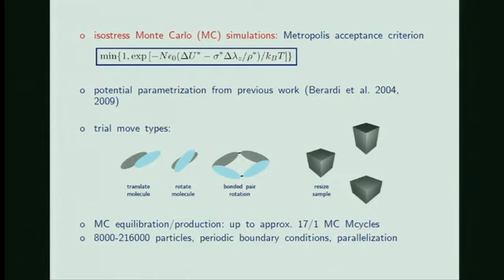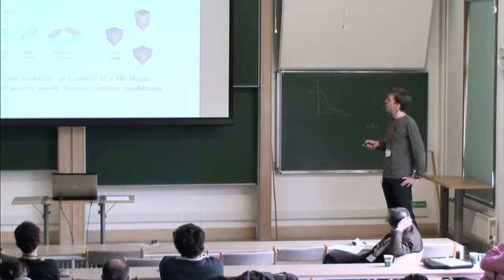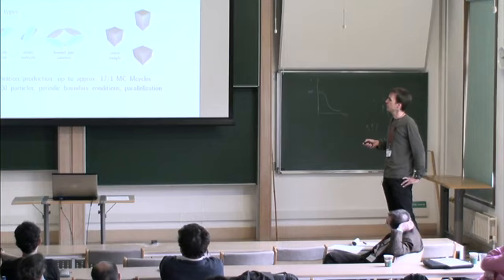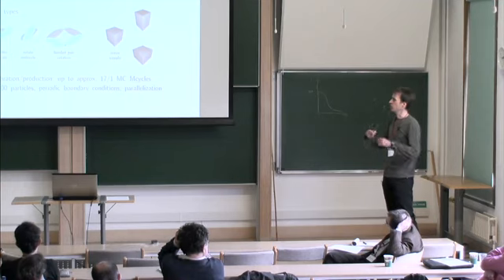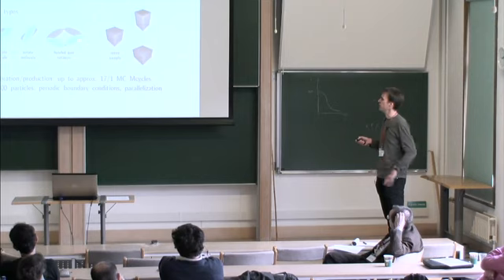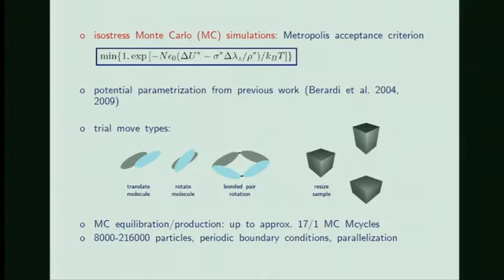We picked this parameterization from some previous work, and the trial moves that we consider here for the Gay-Berne ellipsoids are, first, translating the molecule without rotation. The other trial move type is rotating the molecule without translation. Then, what is essential in equilibrating the chains is rotating bonded pairs. This can also help a lot in equilibrating the system. And of course, if we want to look at macroscopic deformations of our system, we have to implement also collective moves affecting the sample as a whole. So we have these resize moves, which occur at constant volume. We assume the elastomer to be essentially incompressible.